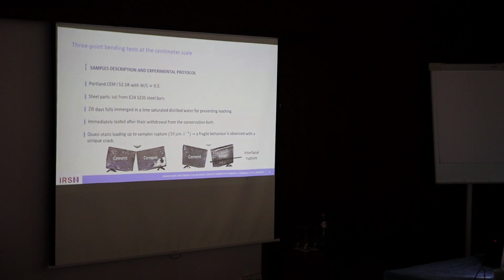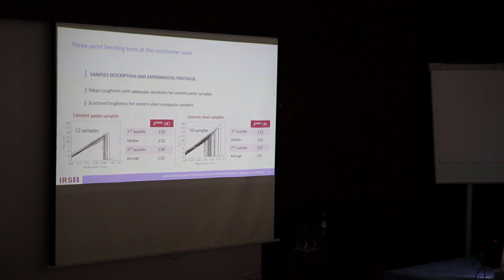And we have observed a fragile behavior with a unique crack developing in the sample. So for the cement paste sample, a crack in the middle from the notch, and for the composite sample, an interfacial rupture. So here are the results of the measure of the ultimate strength for both types of samples. As you can see, for the cement paste sample, experiments were more reproducible than it was for the cement steel samples. And for both types of samples, we obtained an average value of approximately 130 newtons.